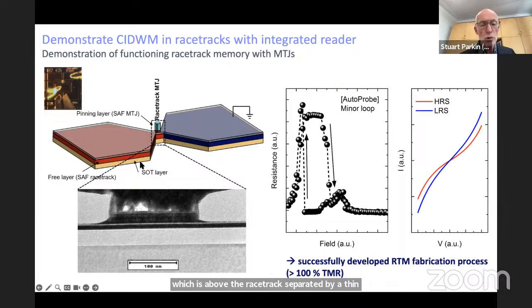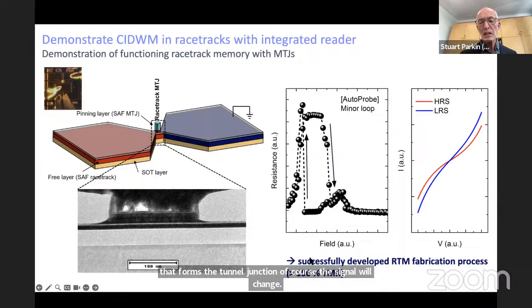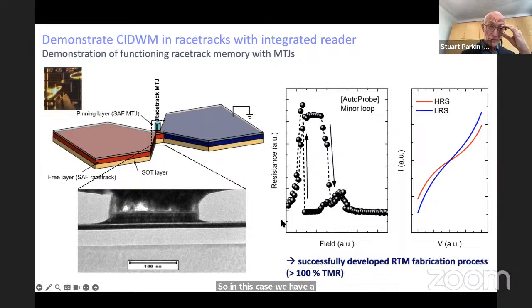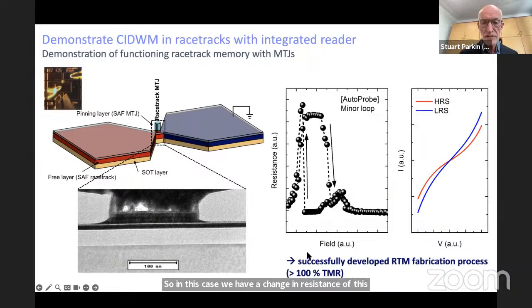So now as the domain wall moves, in this case from the left to the right, underneath this reference electrode that forms the tunnel junction, of course, the signal will change. So in this case, we have a change in resistance of this integrated tunnel junction of about 100%. So it's very easy to detect the domain wall.